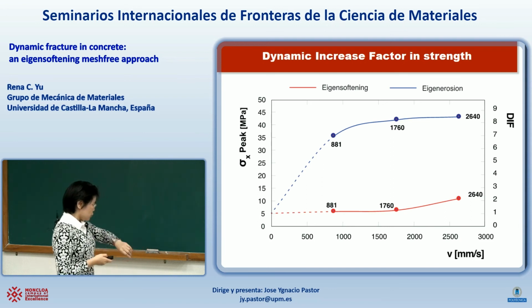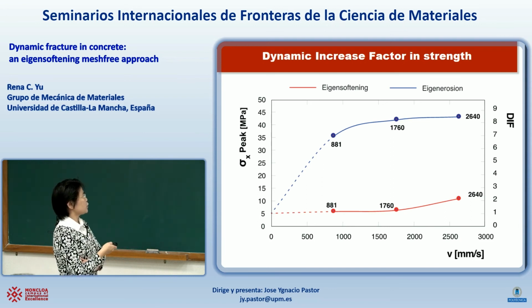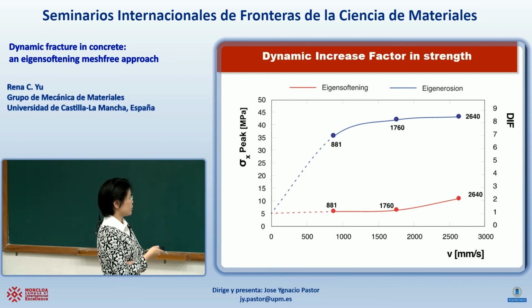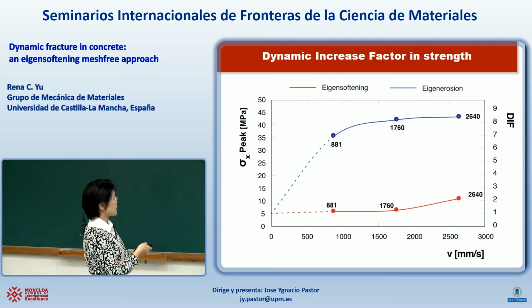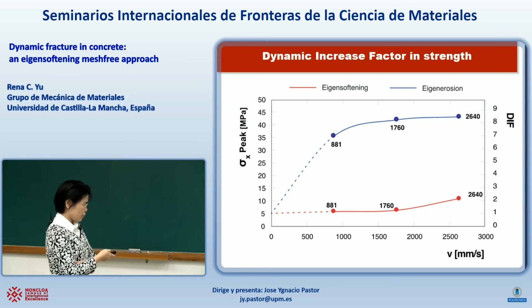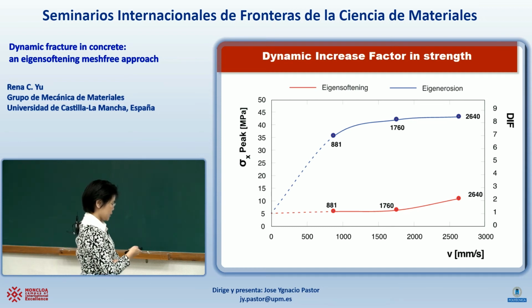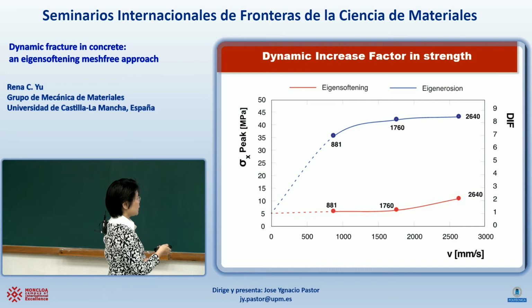So if we want to look at the dynamic increase factor in strength, before we have seen that if we use eigenerosion, the stresses are overestimated, while the eigensoftening that we developed gives a more reasonable number. Because remember, 5 is the static tensile strength. So the dynamic increase factor for those is between 1.1 and 2.2.